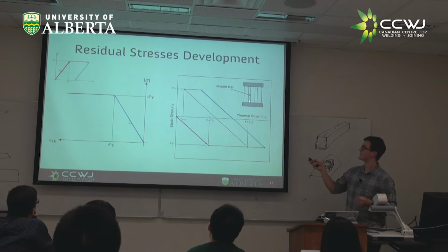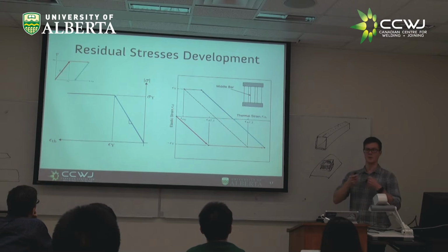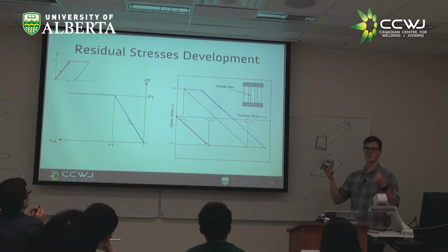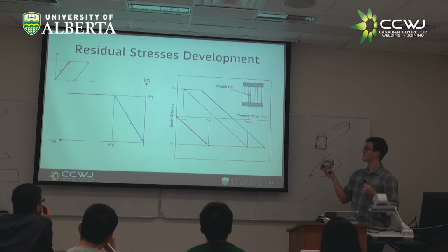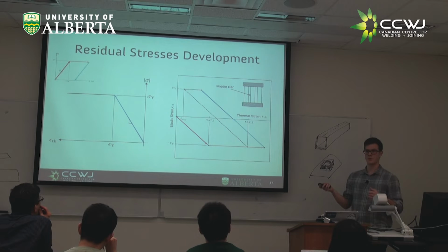So now if you imagine this is that bar, we've heated it up. We heat up to this point where we have all this thermal strain, all this plastic strain, and as we cool, once we get back to our initial length, we still have all this thermal strain and we still have all this compressive plastic strain. So we keep cooling, and then we reach a point where we've actually now, once we cool back to close to room temperature, we're now in tension.